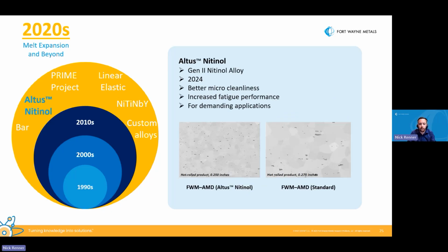Our Altus Nitinol is Fort Wayne Metals' Gen 2 offering, validated in 2024, featuring less than 20 micron inclusions and less than 1.2% area fraction, giving the wire better microcleanliness and increased fatigue performance. Through testing, benchtop RBF, or rotating beam fatigue testing, we have seen equal to or better results compared to other Gen 2 offerings. Currently in 2025, we're focusing on building our inventory to support the wire and bar markets. And you can see in the image below the cross section of our Altus Nitinol compared to our standard, the inclusion size is much smaller.